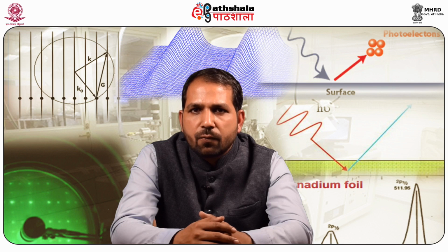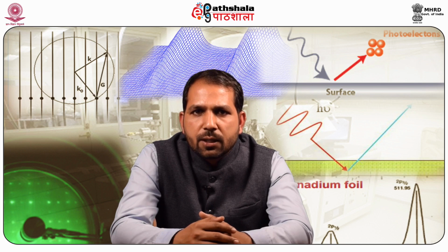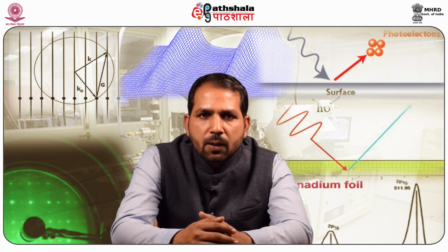The lateral resolutions which can be obtained routinely with probes commonly used today amount to below 100 nanometers for sufficiently strong field variations. Individual flux quanta have been detected on superconductors. The spatial resolution is, however, not sufficient to detect details of magnetization rotation within interdomain boundaries. On the basis of adequate model calculations, it is at least possible to distinguish between different wall types and to deduce other micromagnetic features hardly accessible to many analysis methods.